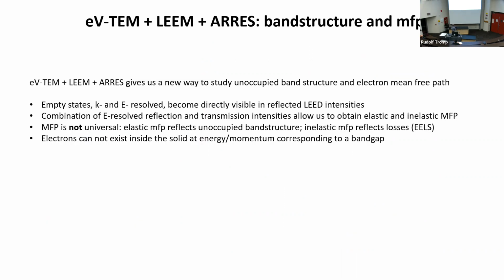So what do we learn from this? It really gives us a new way to look at both unoccupied and occupied band structure, look at mean free paths. You see the empty states, energy and momentum resolved, allows us to obtain these elastic and inelastic mean free paths. The electrons cannot exist at the energy and momentum where there's a band gap. That should be no news, right? If there's no state for the electron to be there, it cannot be there. Yet in all the analysis that I see on angle resolved photoemission data, where you always go from an occupied state to an unoccupied state, that is just always left out of the story. They always pretend like it goes directly into a vacuum-free electron state. That's not true.